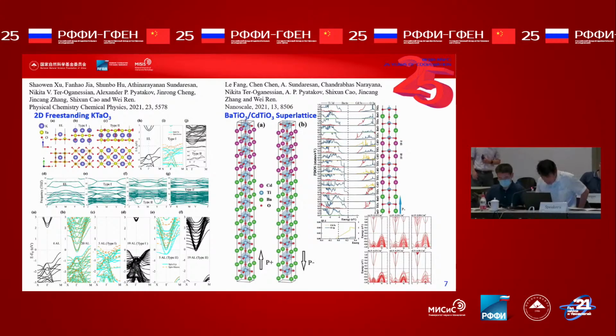Also in this year, we predicted a controllable conductivity with possibly high mobility at the interface of a BTO-CTO superlattice, thanks to the spontaneous polarization of ferroelectric barium titanate. This superlattice undergoes an electronic reconstruction, and there coexist N-type and P-type conductivities in our model system. Using first principles, we found that interfacial conductivity states originate from cadmium 5s and oxygen 2p orbitals with low effective mass and non-degenerate dispersion. It makes it feasible to study transport phenomena, including the realization of fractional quantum Hall effects.